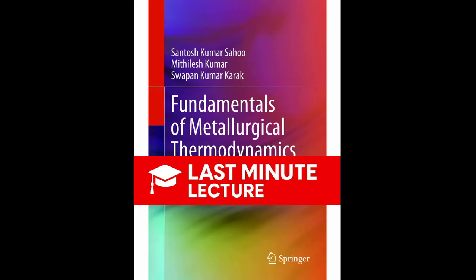But the high-temperature metallurgical environments we care about, smelters, vacuum furnaces, involve gases and vapors that are far from ideal. Absolutely. The source material introduces fugacity, f. Fugacity is essentially a thermodynamic correction factor. It's the effective pressure that a non-ideal gas should have to make the ideal gas equation work for it. So you just swap out P for f. You swap P for f. When dealing with real substances, the relation becomes dG equals RT d ln f.